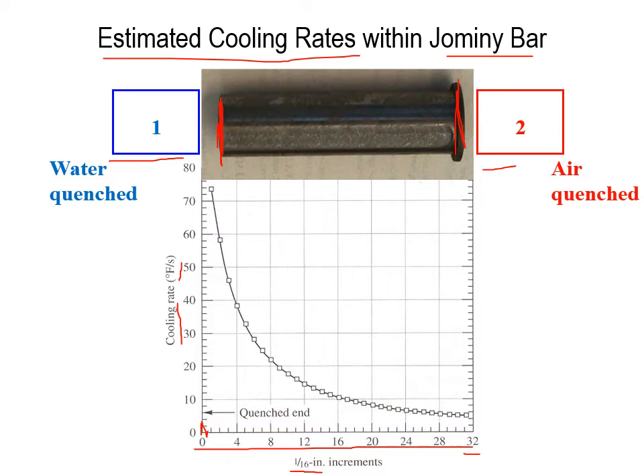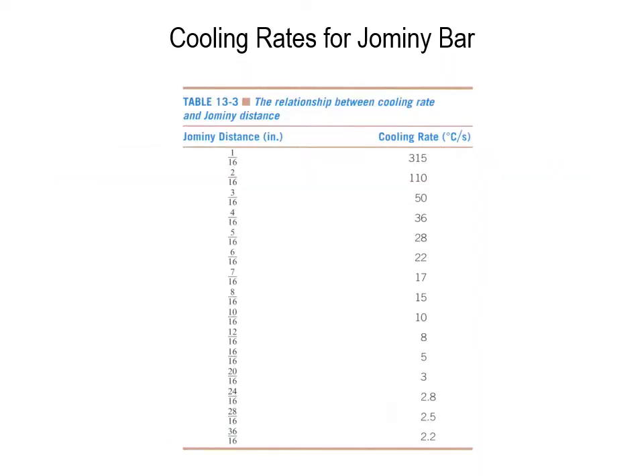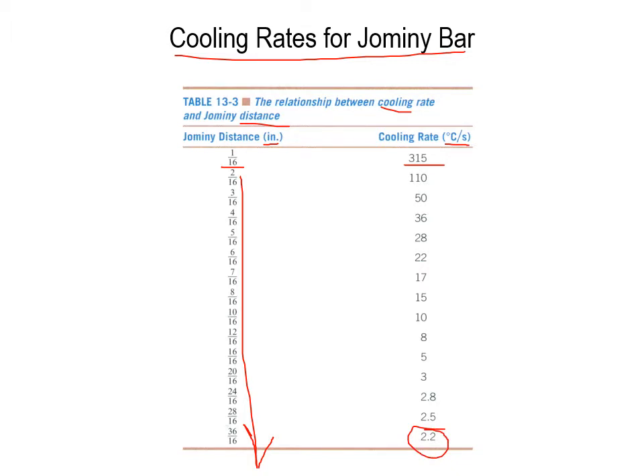So as we can follow the chart here, the further we get away from our end towards our air quench side, our cooling rate is decreasing in this manner. If we look at the cooling rates for the bar in a little T-chart here, we can see our distance, which is in inches, and the relationship between the cooling rate and the distance. So we have a distance of 1/16 inch, and our cooling rate in degrees Celsius per second is 315. And again, as we get further away up to 36/16, our cooling rate drops all the way down to 2.2 degrees Celsius per second.